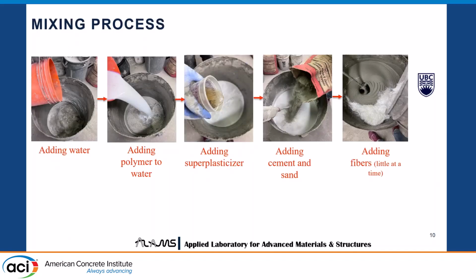So the mixing process is pretty simple. It's a hand mixing. So first the water is added, then the polymer is added to the water. This polymer gives you the early strength, because sometimes people want the GFRC to cure early. Then on that mixture, the super plasticizer, the water reducer, is added. Then the cement and sand is added, like 50% of the cement and sand. Then they are adding the glass fibers, which is added little at a time, and the mixture is continuously turned on. After adding all the glass fibers, the mixing is continued for 5 more minutes. So the total process takes around 12 minutes from adding water to the completion of fiber addition and mixing.